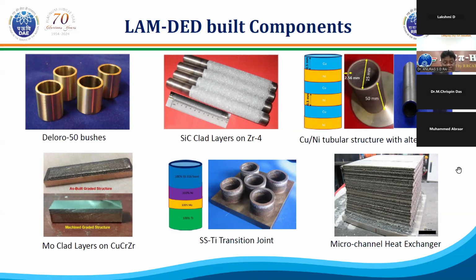An SS titanium transition joint is built, and we also built a micro channel heat exchanger that you are seeing on the right bottom corner. These channels are about 2 millimeter by 3 millimeter rectangular channels across the job. And the job size that you are seeing is about 250 millimeter by 250 millimeter by 250 millimeter. So you have a cube. And again, it took a long time for us to build.